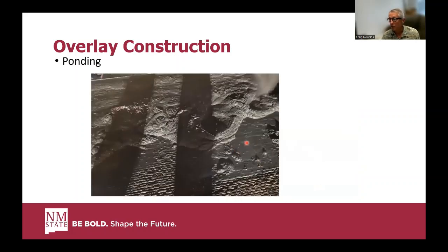So at the very beginning of the first placement, there was a ponding issue, a little bit of excess water. It was a small area, maybe 100 square feet total. In testing after construction, we actually don't see any issues in that area. Everything looks great in that area, but there was some concern. Basically what they had was a hose that was leaking and running down and ponding at the low end of the pour. Everything turned out well off of that anyway.